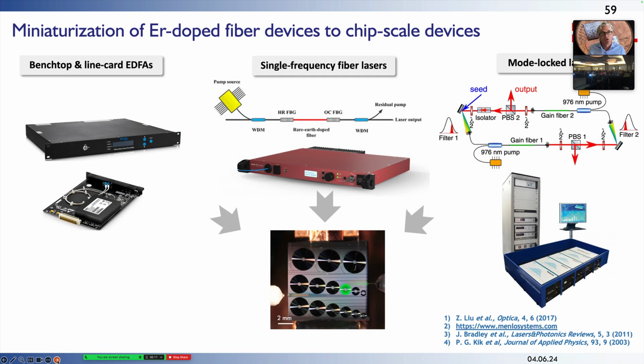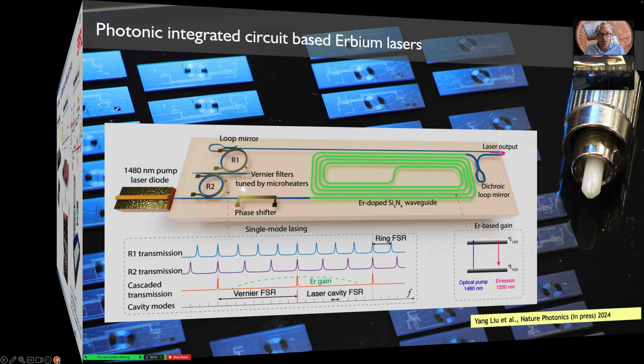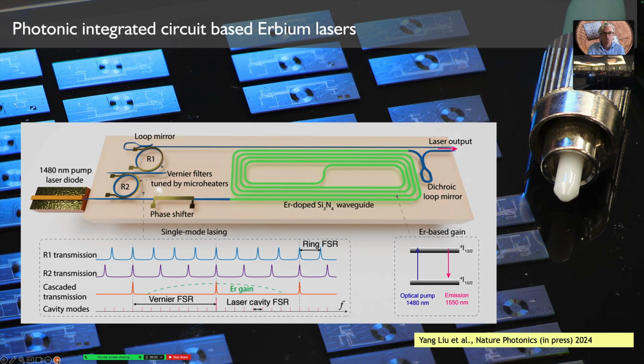But there are more devices you can generate. You can not only generate amplifiers, but also single frequency lasers, or in the future potentially even femtosecond mode locked lasers on chip. To give you a glimpse of such a device, which can also be enhanced and actuated with piezoelectric actuators like PZT or AlN, this is an example of a 70 centimeter spiral that is selectively implanted on chip. We have frequency selective elements, and this device serves as a tunable erbium doped laser that can cover the full C and L band.